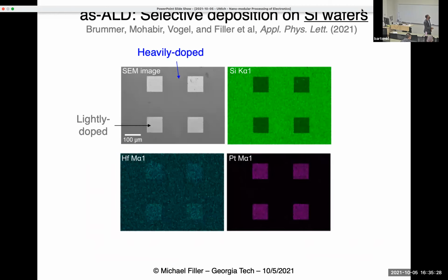If you look at it in an EDS map, this is the SEM image, and you can see by looking at the hafnia X-rays and the platinum X-rays that the hafnia is where we expect it to be, and so is the platinum right on top of it. This is really light here because the hafnium X-ray overlaps with the silicon X-ray a little bit. Okay, but it basically shows that we can make these capacitors on a wafer using this polymer process plus area selective ALD.